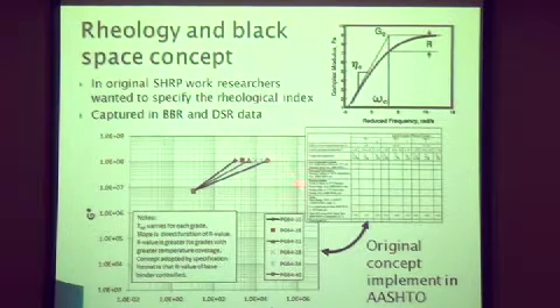Now, in the specification that got implemented, because we have both BBR and DSR on the same aging condition, both on PAV, we have the rheological index effectively by default. Rheological index, the complex modulus frequency master curve, and I'll show you that in some other graphs. Look at complex modulus versus frequency, or complex modulus plotted against phase angle. Related to cracking, related to something called the relaxation spectrum of the binder. It's very important for controlling cracking.